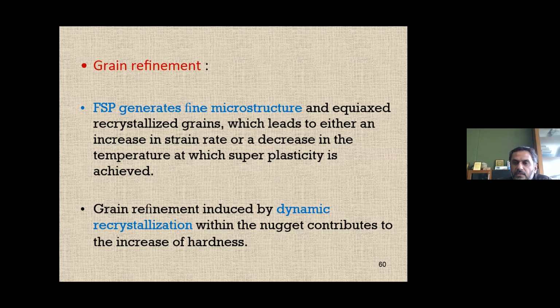Now if you are getting a superplastic behavior at very high temperature, which is not advantageous for a commercial application. But if you are getting superplasticity at a lower temperature, which is more advisable from an industrial perspective, and the rate at which you are getting strain rate, right? If that is slow, then it will take a long time. So the lower the strain rate, the more time it will take. So a higher strain rate and a low temperature is more preferred for superplasticity from a commercial angle. And the grain refinement induces dynamic recrystallization.